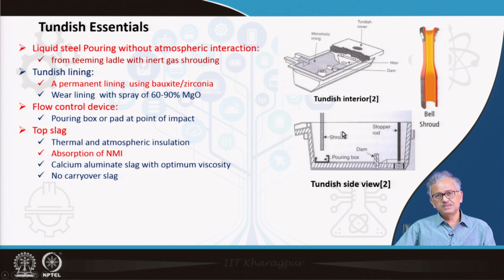In this case, because it is highly reducing, the oxygen percentage in the liquid steel is still very low. So it is a highly reducing condition, and all these oxides will have a propensity for breaking, because the linings are made of alumina in most cases. So SiO2, P2O5, FeO will be very reducible in the presence of aluminum. As a result, they can supply oxygen into the liquid steel, and that can in future form a lot of inclusions. So no carryover slag at this point is allowed.